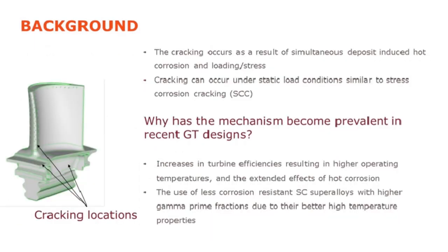A bit of background then into why this is happening. We believe the cracking occurs as a result of simultaneous deposit-induced hot corrosion, I'll talk a bit more about what that is in a bit, combined with loading or stress. The cracking can occur under static loads as well as fatigue cycling. So it's a bit of a stress corrosion cracking type mechanism, similar to what we would see in aqueous stress corrosion cracking at, obviously, much lower temperatures typically.